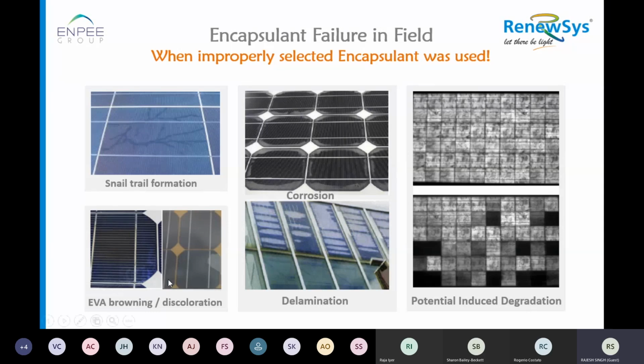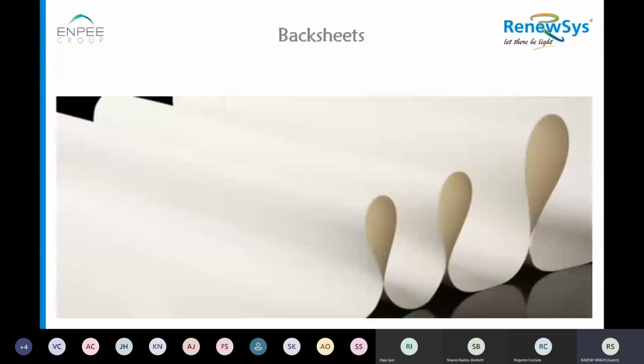Then we have EVA browning or discoloration. This is again caused by wrong selection of raw material while making encapsulant, and it could also lead to delamination. This could be caused by wrong formulation of EVA while manufacturing. And PID we discussed, it could be caused because of current leakage through EVA, and then it actually affects the cell. Finally the cell gets damaged at PN junction level, and it stops generating power, which is what it is expected for.